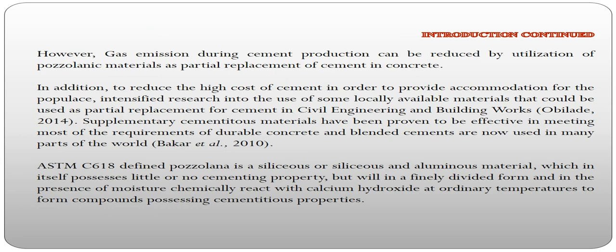However, gas emission during cement production can be reduced by utilization of pozzolanic material as partial replacement of cement in concrete. In addition, to reduce the high cost of cement in order to provide accommodation for the populace, intensify research into the use of some locally available material that could be used as partial replacement of cement in civil engineering and building works. Supplementary cementitious materials have been proven to be effective in meeting most of the requirements of durable concrete, and blended cements are now used in many parts of the world.